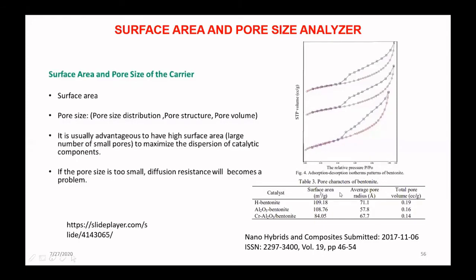There was an increase in surface area. For example, bentonite is 109. No, the surface area is not very affected, but there is a decrease in the pore due to introduction of chrome into the interlayer. Why is the surface area not significantly different? Because bentonite has a dynamic interlayer. It is a very hygroscopic material compared to the alumina bentonite, from the structure.